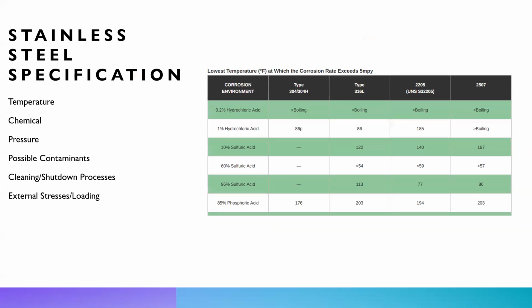So stainless steel, it's very similar to Belzona as far as when to use it. You look into your temperature, your chemical, your pressure, your possible contaminants, your cleaning, shutdown processes, external stressing and loading. Just like our products, they'll have a chemical resistance chart, which shows your corrosion rate. There's times when stainless steel is a great specification. There's times when it might not be the greatest time to use it, especially when you have chlorides, or if you can get away with using a carbon steel or a carbon steel coated. So economically, you have to look into that as well.